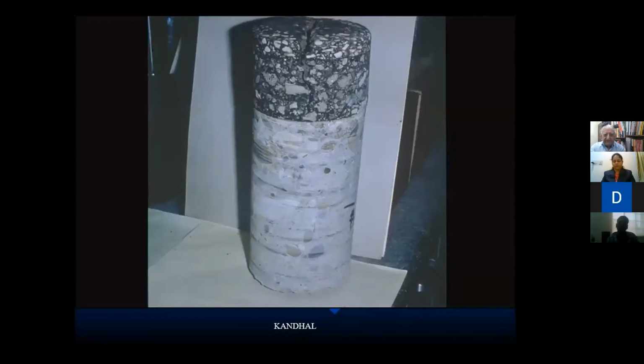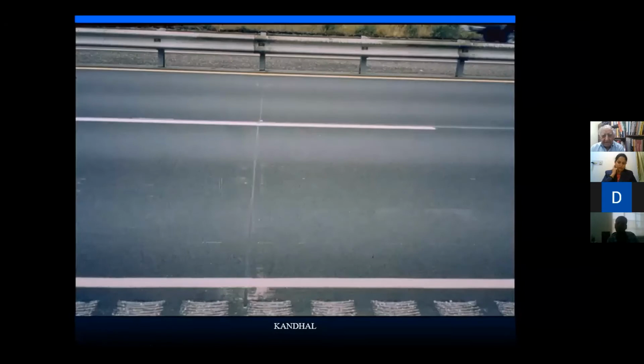So what I will do, I'll take a core right on the crack itself. And here I took a core, and there was a cement concrete underneath, I know. But the crack you can see in the bituminous concrete here, but there is no joint here. If it was a reflection crack, I would see a joint or crack in the cement concrete. I don't see it here. So it's not a reflection crack, it's a thermal crack. So that's how we find it in here.